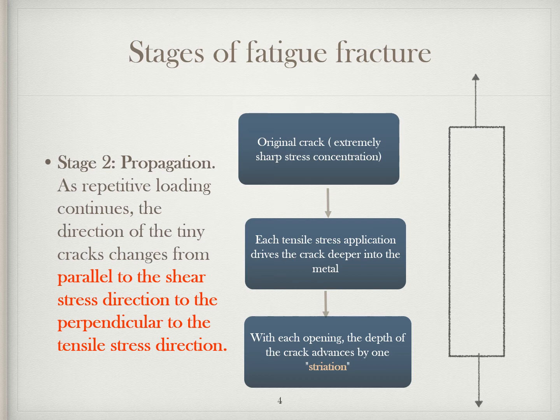The first or initiation stage of fatigue causes a microcrack parallel to the shear stress component, while the second or propagation stage of fatigue fracture causes the microcrack to change direction and grow perpendicular to the tensile stress. This is the same direction as taken by a brittle fracture, although fatigue is caused by a different mechanism and by a much larger number of load applications than is a single load brittle fracture.